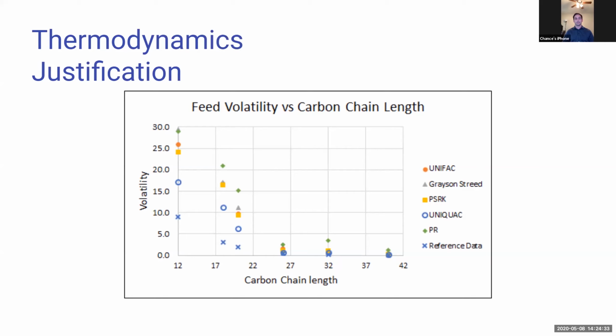And so you can see those blue X's denote the reference data, whereas all the other points denote our simulated feed data based on which thermodynamic model we were using. So you can see we used UNIFAC, Grayson-Streed, PSRK, UNIQUAC, and Peng-Robinson. And out of all those, it seems like the UNIQUAC was the best fit. So we decided to use the UNIQUAC moving forward.